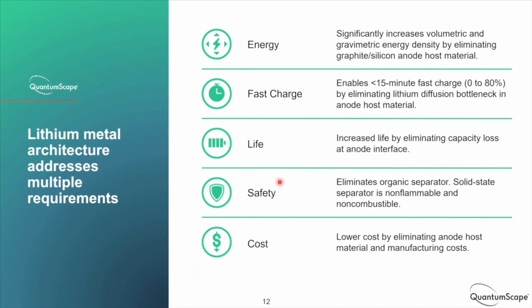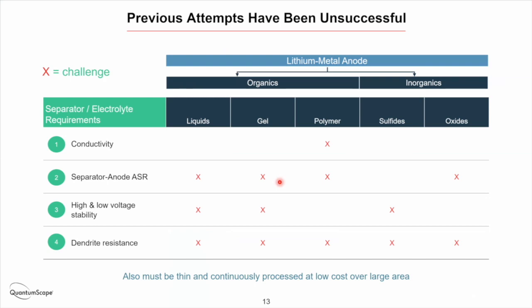Now, as I said, we didn't invent the lithium metal anode. That concept has been around for decades, but it has been hard to commercialize. And this is why you don't see a lot of cars today driving around with lithium metal anodes. So people have tried various different separator chemistries between organics and inorganics. There are many families of materials that have been attempted to work with lithium metal: liquids, gels, solid polymers like PEO. Among inorganics, sulfides and oxides are the most popular classes. Also emerging over the last few years are halides, borohydrides. Unfortunately, all of the materials that have been tried have real challenges on at least one, if not more, of the key metrics for the separator.